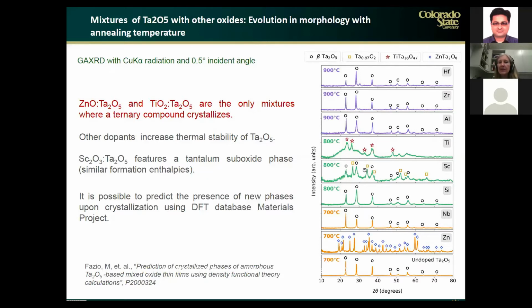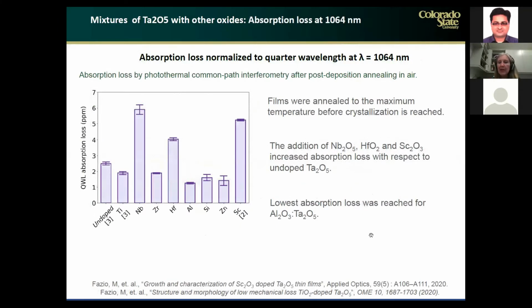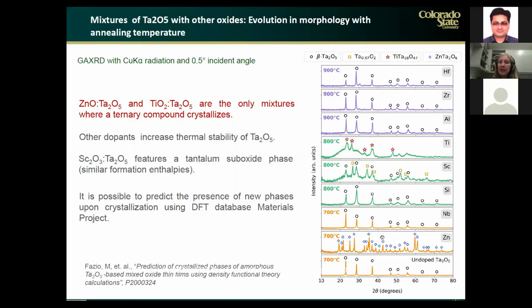There are some other alloys, like for example, scandia, in which we observed phase separation. And in this particular case, the phase is identified as a tantalum suboxide. And so what this means is that there is competition between tantala and scandia that gives rise to this formation of this suboxide. But what we showed is that when we add zinc, we observe exactly the same behavior as with titania, in that we anneal the zinc and we identified a new phase, which is a zinc tantalum oxygen phase.